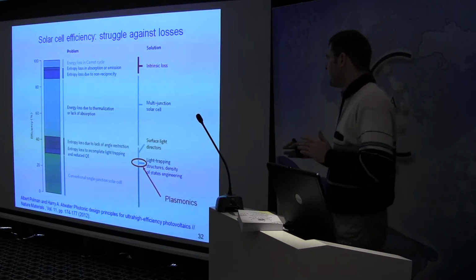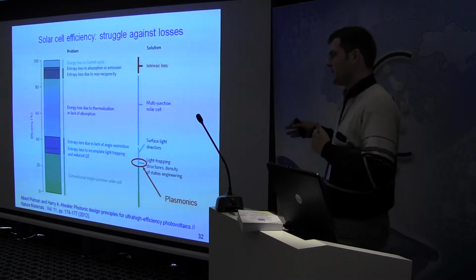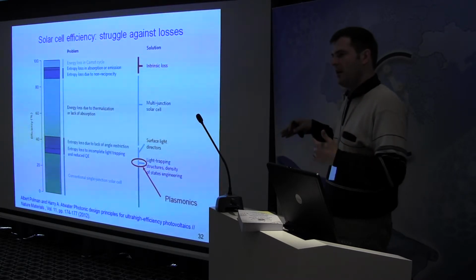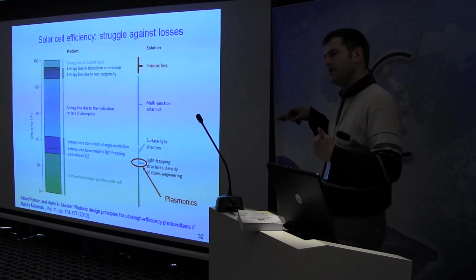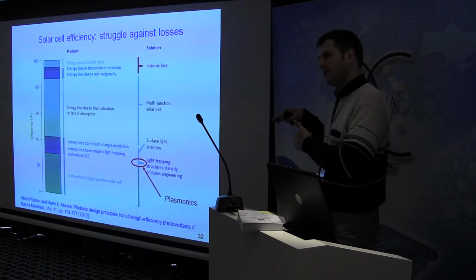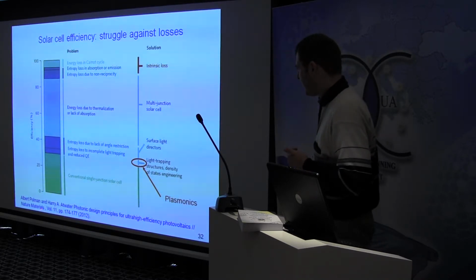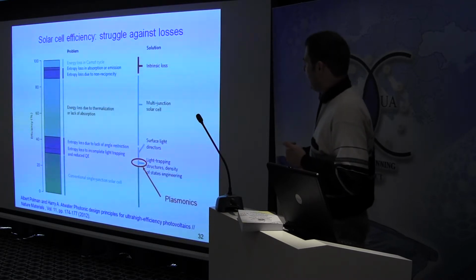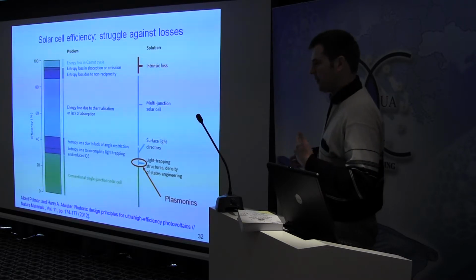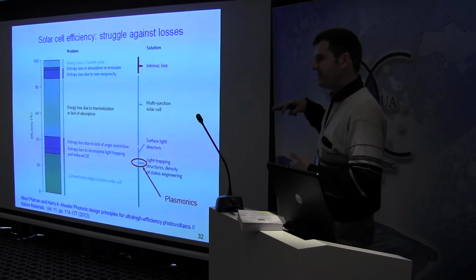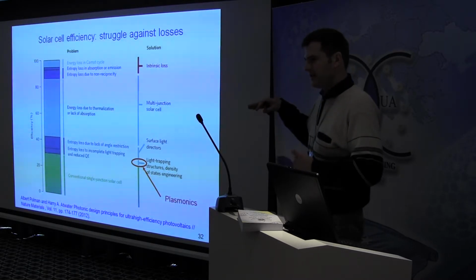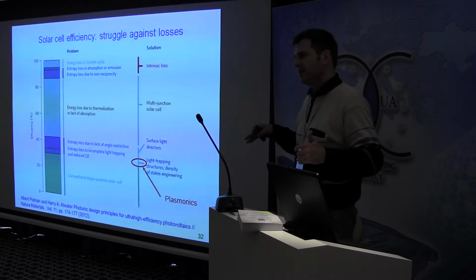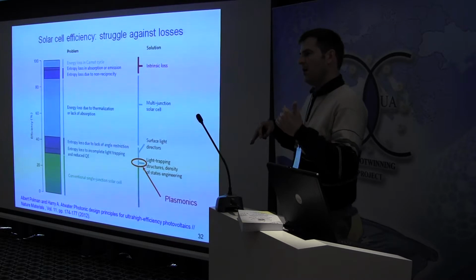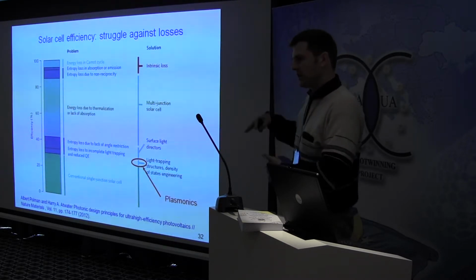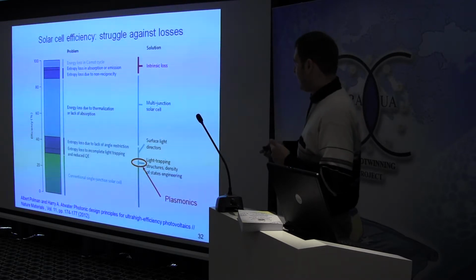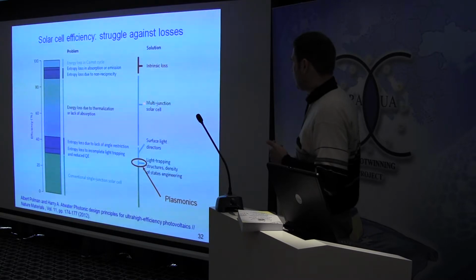And in conclusion, it's very useful to have a general overview of where we can gain in efficiency when we use plasmonics. So how large can the maximal efficiency be if you use plasmons? And here I found a nice diagram in this review paper. Here you see that increasing the efficiency of a solar cell is a struggle against the losses. It means we cannot have an ideal material, or an ideal structure which will allow us to use all of the incident light. But it is possible to struggle against it, to improve the structures, and you see that the most efficient way to improve is the multi-junction solar cell.